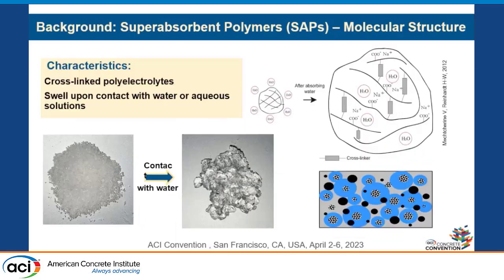My previous study showed me that SAP, or superabsorbent polymers, are a really good candidate to solve the problem. Superabsorbent polymers are cross-linked polyelectrolytes that swell when they absorb water, and it takes some time to release the water into the matrix. This gradual release of water means we can use SAP as an internal curing agent, as you can see there.